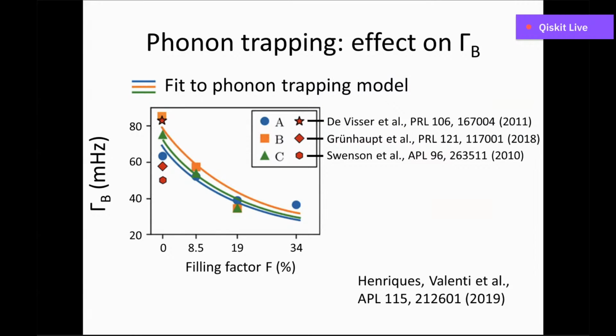What I show in this slide, in this graph, is the burst rate. How many quasi-particle bursts do we observe over time as a function of the phonon trap coverage, the phonon trap filling factor, for our three resonators A, B, and C. And we can appreciate that this rate is decreased monotonically for all our resonator types.